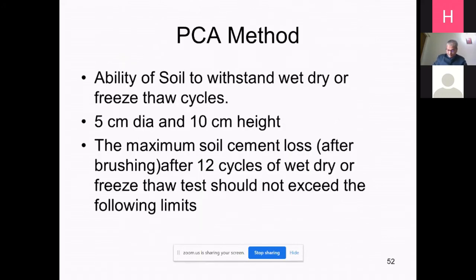The second method is the Portland Cement Association method. In this also the same 10 centimeter height, 5 centimeter dia samples are made with different cement contents, and there are 12 cycles of wet-dry or freeze-thaw tests. After each cycle, you put the sample in water, take it out, dry it, and then brush it with an iron brush, and again put it in water. That way 12 cycles are made, and you find out the loss in weight after 12 cycles.